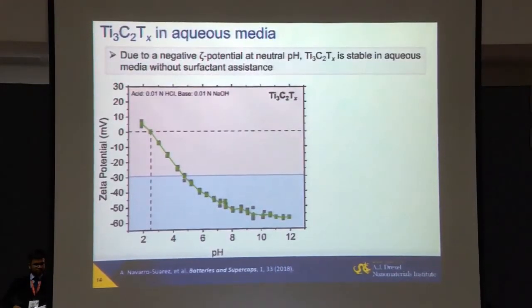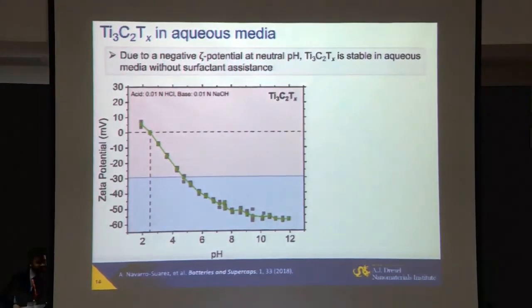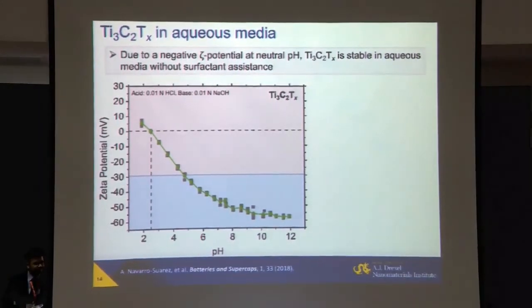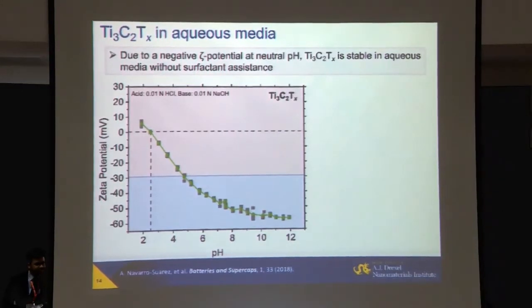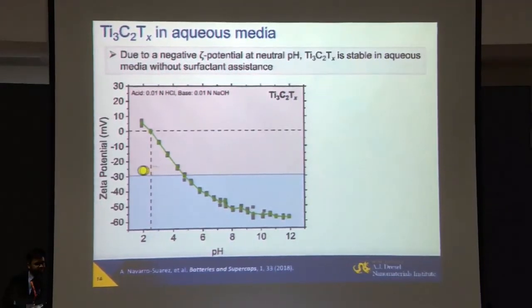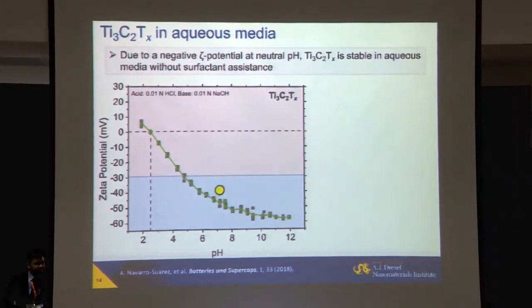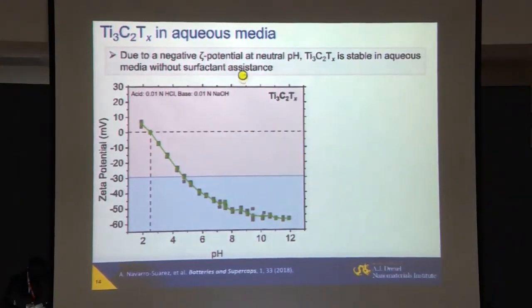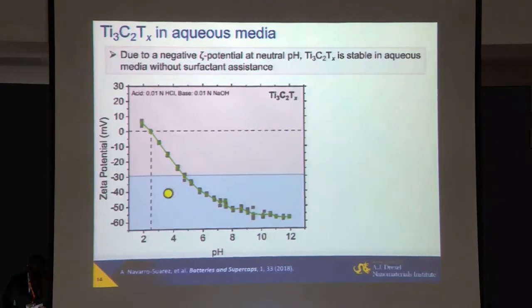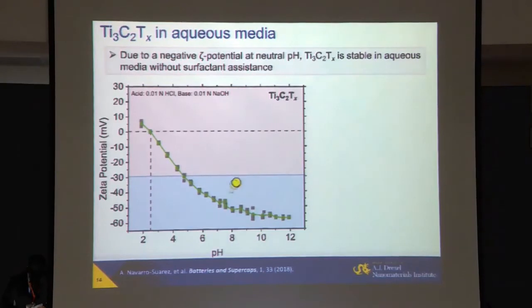Moreover, what is also very useful in the majority of applications is that we don't need toxic solvents to disperse them, because unlike hydrophobic graphite or graphene, they can be dispersed just in water. Because, going back to your chemistry background, if there is a zeta potential which is below roughly -30 millivolt or above plus 30, material forms stable colloidal solution. So you see near neutral pH, MXene will, and this is titanium carbide Ti3C2 example, form a nice colloidal solution.